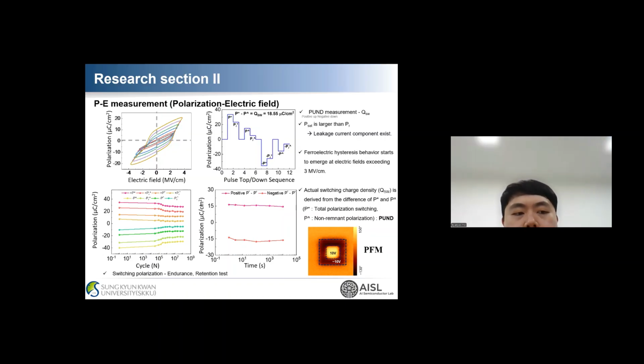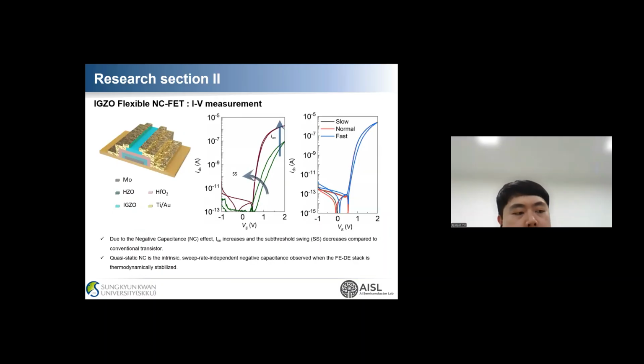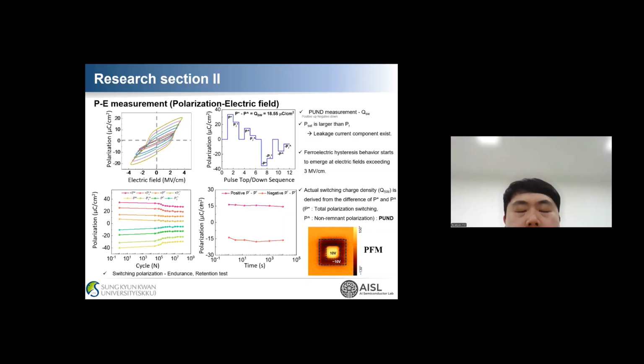We also evaluate the reliability through endurance and retention tests. The device maintains stable ferroelectric behavior up to 10 to the 7th cycles and 10 to the 4th seconds. In addition, PFM measurement confirmed the piezoelectric response, showing clear switching behavior under plus 10 volt and minus 10 volt bias.